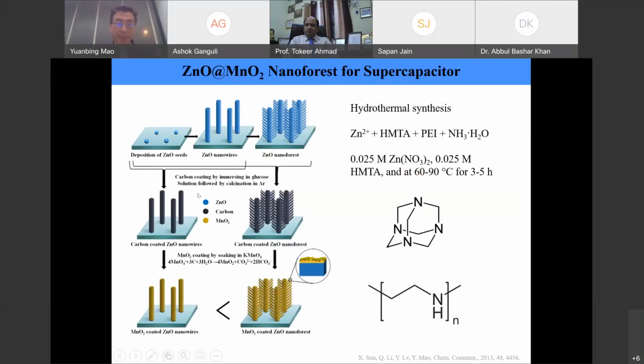It is basically based on a redox reaction between the permanganate and carbon. First we coated the zinc oxide nanostructures, either nanowires or nanoforests, with carbon. We use both because we want to compare which one has a better performance. Then, through this reduction process, we convert the carbon into manganese dioxide. So this type of zinc oxide nanostructure becomes manganese oxide coated zinc oxide nanostructures,